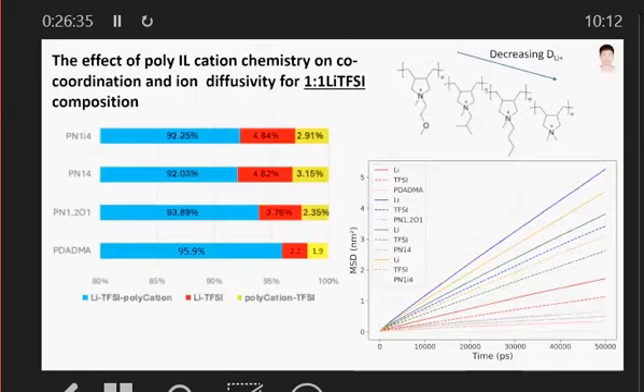Right. So we do again some typical characterization in the MD simulation. The two things I'll show you here are the coordination environment here for the lithium TFSI polycation here. Again, it dominates. The Li TFSI here, and then the polycation TFSI system here. So you can see this is the 1:1 TFSI. TFSI is not as soluble as FSI, so we've gone to 1:1 in the simulation box. So these aren't that different, to be honest, but if you look at the mean square displacement evolution here, which is what we measure the diffusion coefficient from, the slope of this line is a diffusion coefficient.